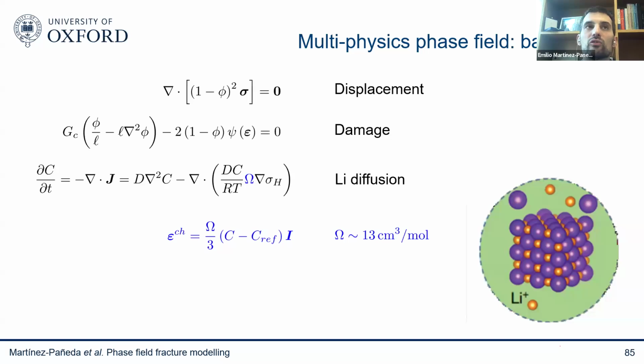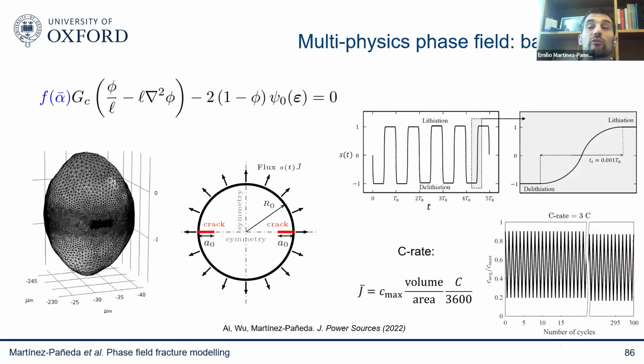And a few people have already looked into this problem with phase field fracture methods, but all of them were simulating only half a cycle. But this is, of course, a cyclic process. So we developed the first phase field fatigue model for this, where again we have a fatigue degradation function. And this was work done by Wei Long Ai, who was a postdoc of Billy Wu at Imperial, and is now an academic in China.